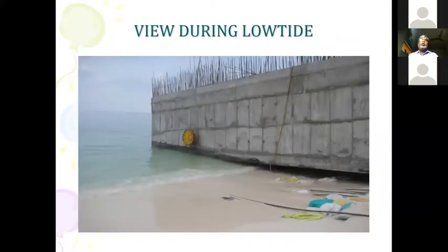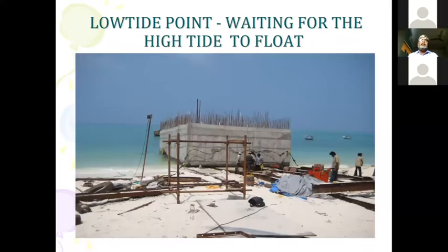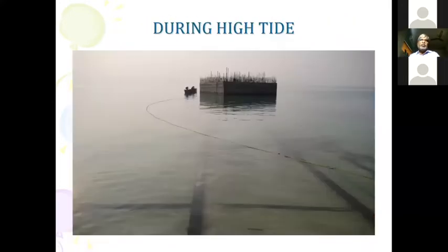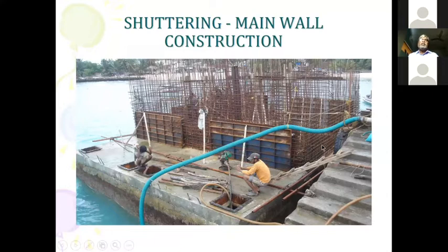So this is during the low tide level, and once you get the high tide level, it starts floating, and then you just bring it out through the mouth of the island and bring it to the fisheries harbor jetty, which is already there and is being used by the Lakshadweep Harbor Works. And the further constructions have been done, and later on, taking this and putting it in position, we'll be filling this with pig iron, or otherwise with blue metal of 40 mm, so that the dead weight calculation goes as per the design calculations.